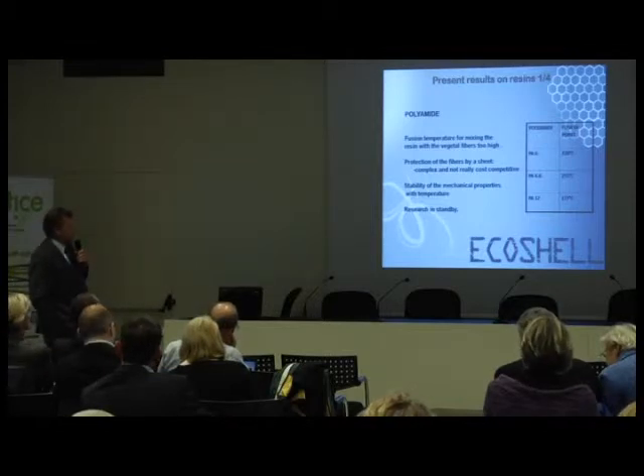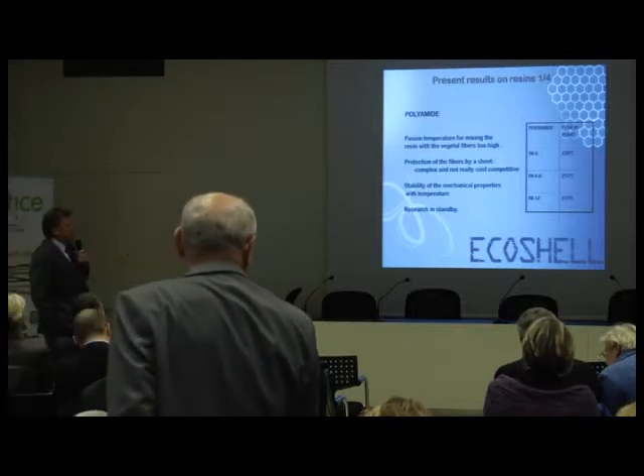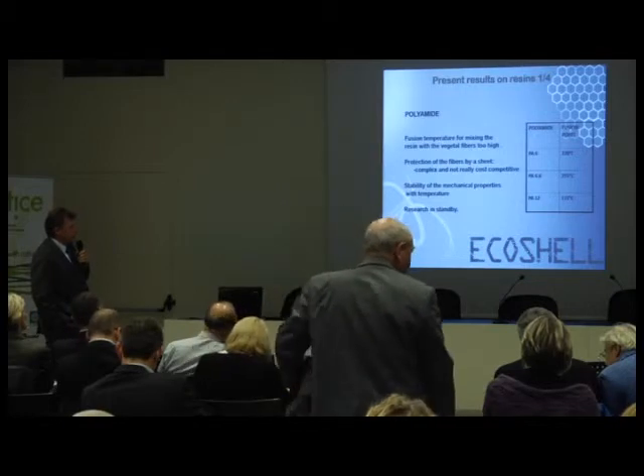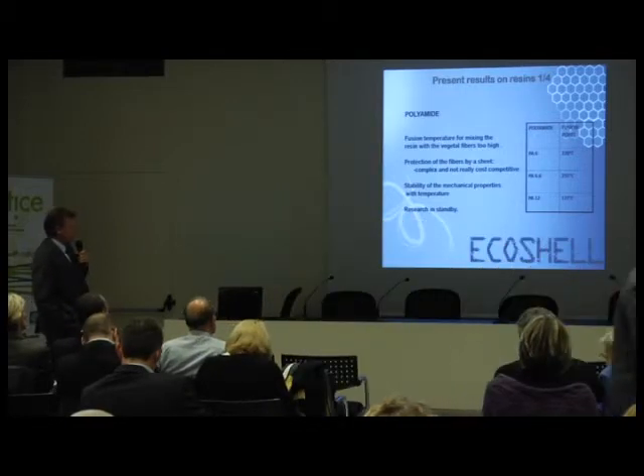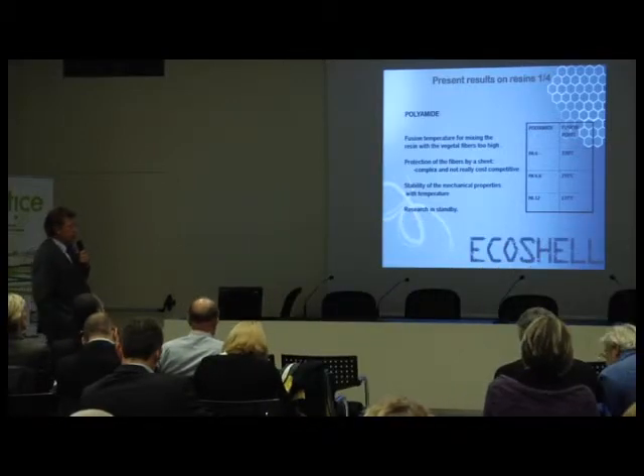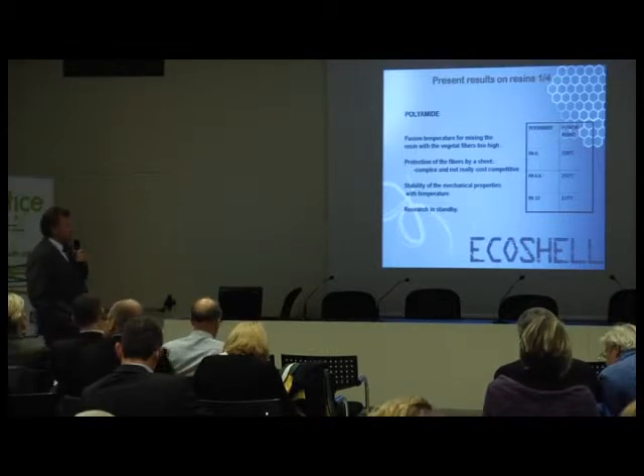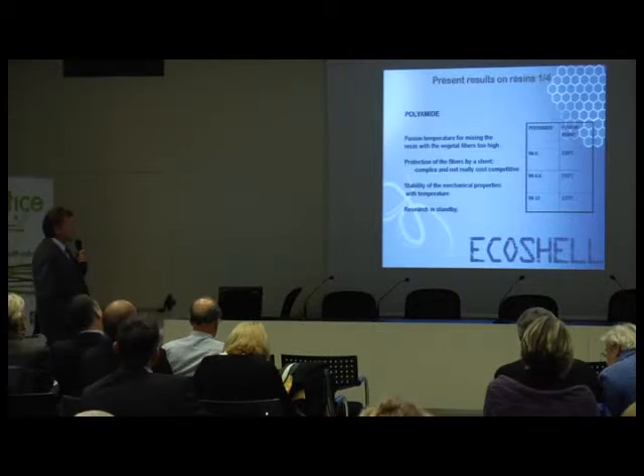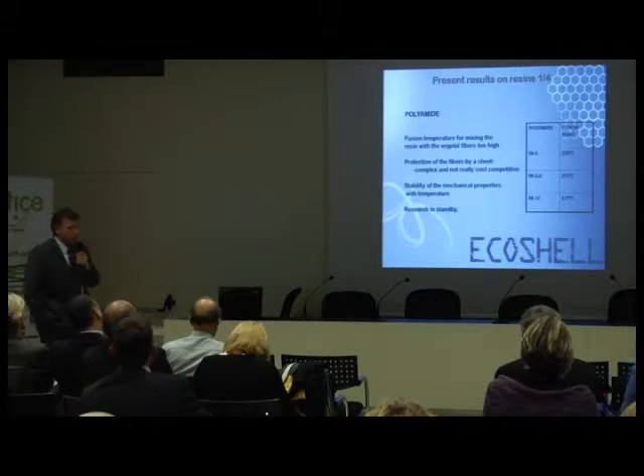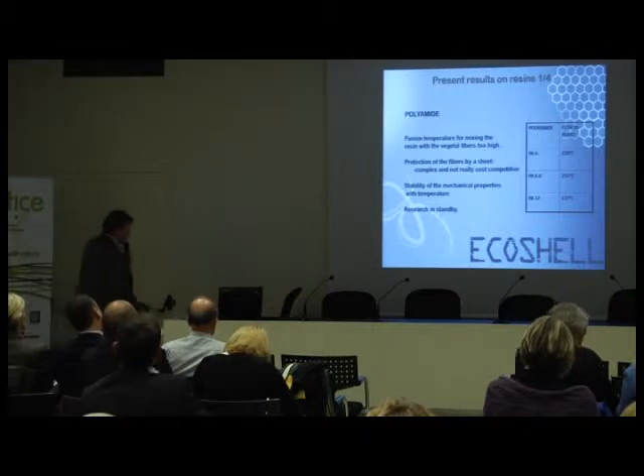When we try lower-property polyamide such as polyamide 12, whose fusion temperature is close to 170 degrees, we have a problem of stability of the mechanical properties at high temperature. So today we stopped the work on polyamide, trying to find another resin.